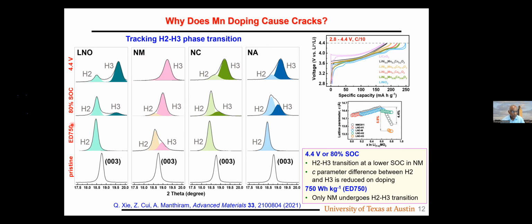This is the cutoff energy density of 750 watt-hour per kilogram. Again, in that case, none of them show the H3 phase excepting manganese. So the first point we need to understand here is that the H2, H3 phase transformation does not occur at the same lithium content or at the same state of charge. It is different, particularly in the case of manganese doping. It occurs at a slightly lower state of charge. That's why we have this issue.